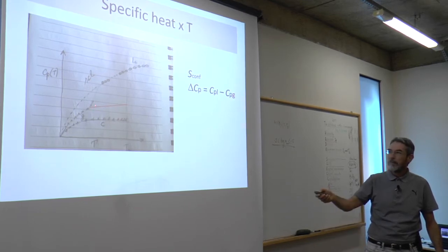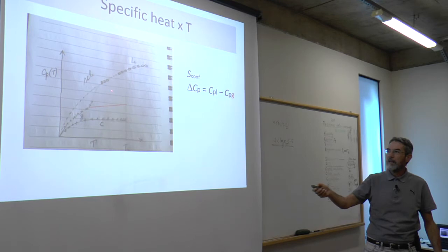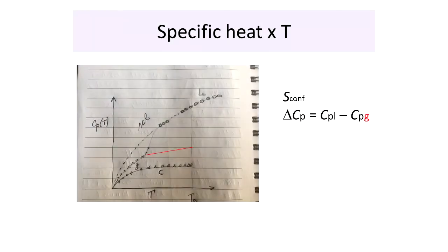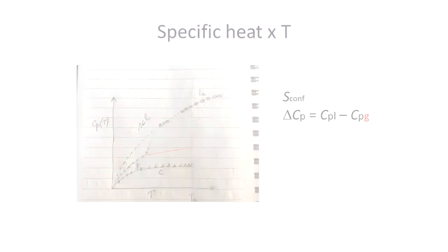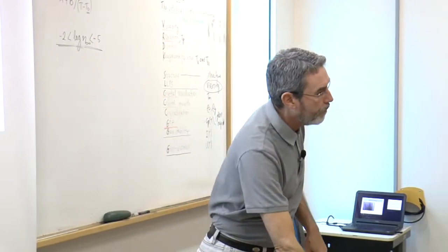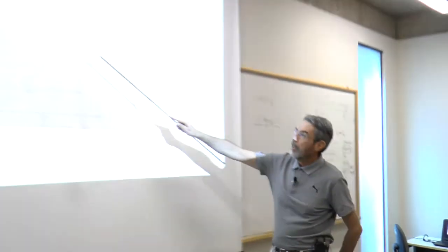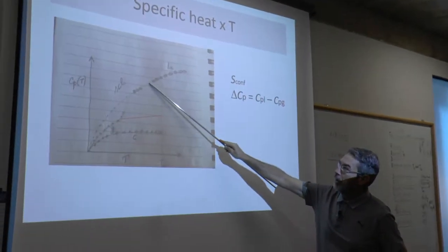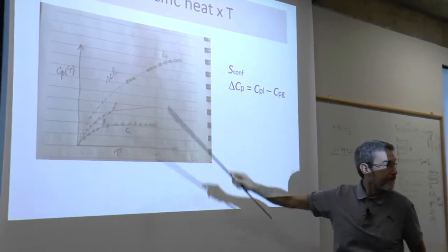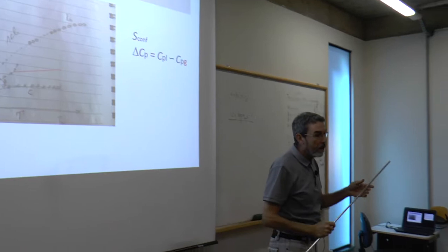So this will be the only problem, to extrapolate here and to interpolate here. Some glasses, like for instance B2O3 glass or albite glass, are very, very stable against crystallization. So for those types of supercooled liquids, one can get data points even here. If they don't crystallize, you can get data points all the way here. But the glasses you are working with